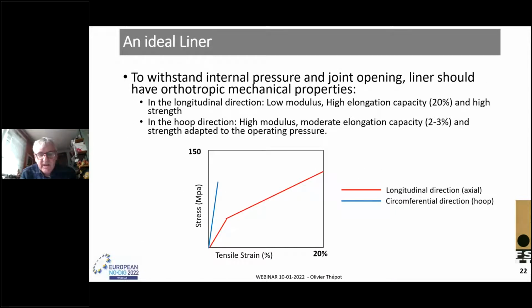In view of the experimental results and our analytical model, it appears that the ideal liner should have very different mechanical characteristics between the circumferential and longitudinal direction. In the longitudinal direction, the material should have a low Young modulus, a high elongation capacity, about 20%, and a high strength. In the circumferential direction, also called the hoop direction, the material should have a high Young modulus, a moderate elongation capacity, and a high strength adapt to the internal pressure.